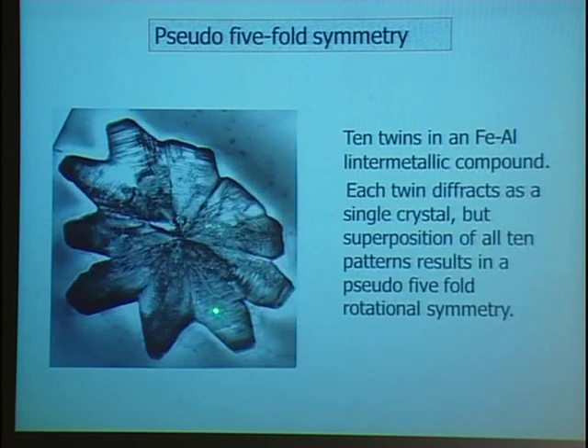Right here, down here, it's a periodic crystal. Here is another one, here's another one. If you count them, there are 10 altogether. This is very common in the aluminum iron system. What's special about these crystals is that they are twin related. So between this and this, there is a twin boundary. A twin boundary is a mirror boundary, and planes from this crystal have a mirror image in the other crystal. So this is a twin boundary. I'll show you later on a lattice image of something like that.